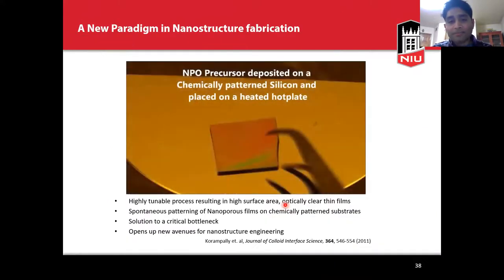Okay. All right. So here, this is again going back to our own research. What we have done here is using the substrate effect, the surface of the substrate itself, to drive the nanoparticles to assemble in different ways. Of course, before I play the video here, what I want to show is you have a film of nanoparticles and polymer deposited over a surface, where I have modified the surface to be different in different regions with different chemical functionality. Now, the moment I place it on a hot plate, the nanoparticles are given energy, the heat energy, and the nanoparticles move, they self-assemble themselves. And depending on the substrate itself, depending on the region where they are present, they assemble into dense regions or highly porous regions.